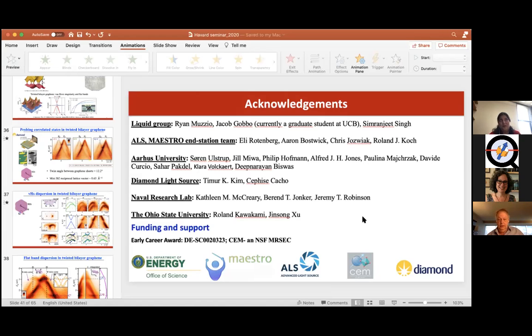One thing we've done, both things actually. We have made devices here and not wire bonded them, taken them to ALS, and then wire bonded them there and measured them. But for Diamond, when we went to the Diamond synchrotron, we actually wire bonded them here and shipped them. And fortunately, this arrived. But in general, for 2D materials, so far we've done work where they were not air sensitive, so it was not a problem, and when we take them over there, we do anneal them by heating them. So we anneal them in ultra high vacuum, and that helps to get rid of any adsorbed gases or water on the surface.